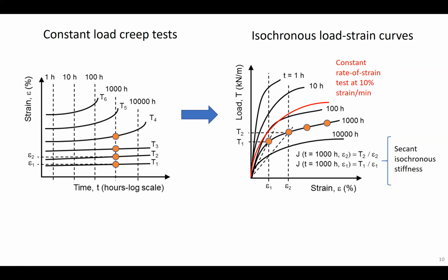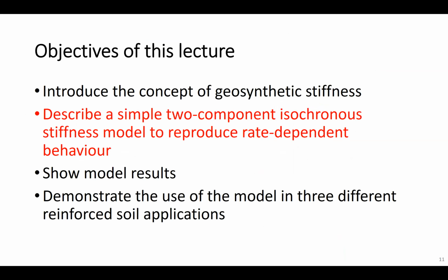The secant isochronous stiffness at particular load and strain is simply the slope computed at load T and strain, as you see here. If I can find an equation for the isochronous stiffness for each isochrone, I can compute the tensile load at a given strain and time, with time matching that isochronous time. And equation J is called the isochronous secant stiffness. And the question then is how can I find the form of this equation? And this leads to the development of a simple two-component isochronous stiffness model to reproduce rate-dependent behavior.